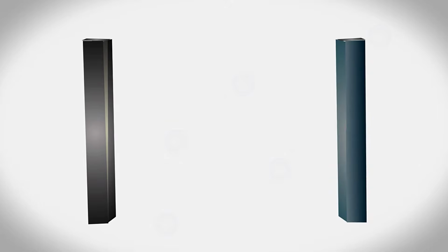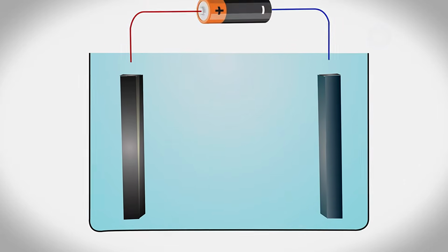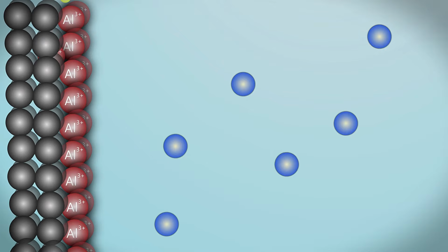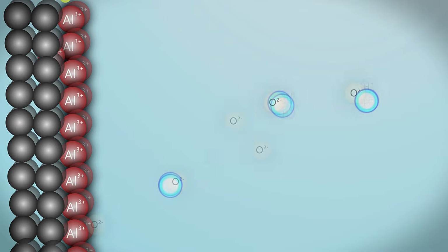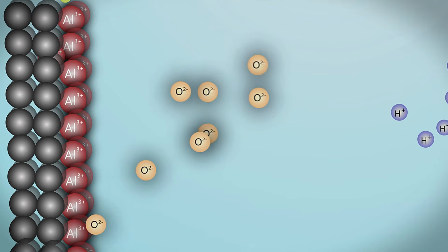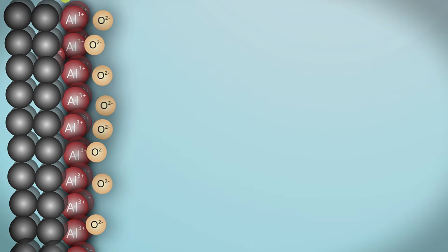Aluminum instantly forms a natural oxide skin just a few nanometers thick when exposed to air. Anodizing is what happens when we supercharge that process. During anodizing, aluminum is connected as the anode, another metal as the cathode or counterelectrode, and a voltage is applied. At the atomic scale, aluminum atoms at the surface give up electrons and become aluminum ions, Al3+. Meanwhile, water in the electrolyte splits. Oxygen species drift into the metal, aluminum ions drift outward.